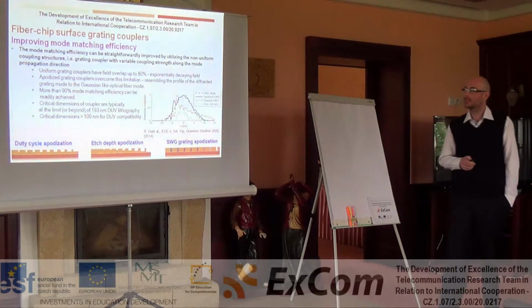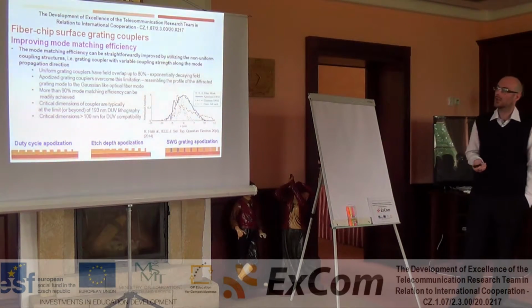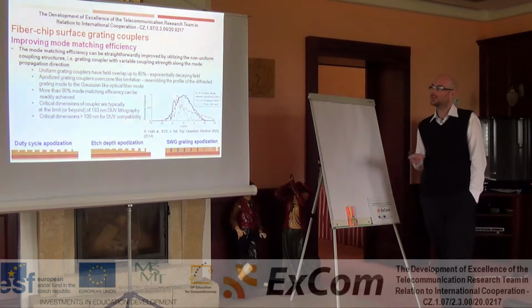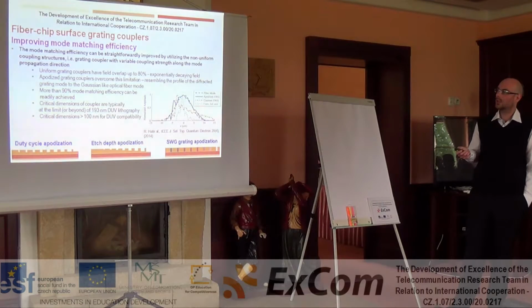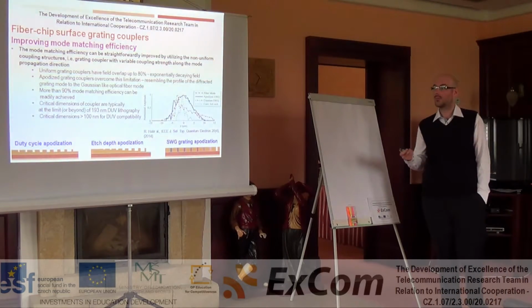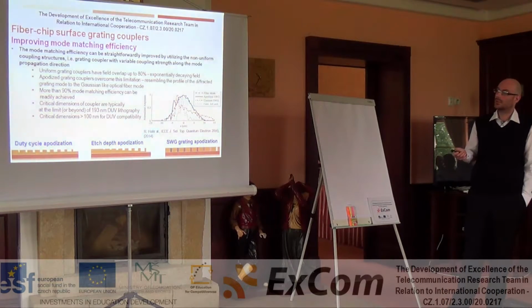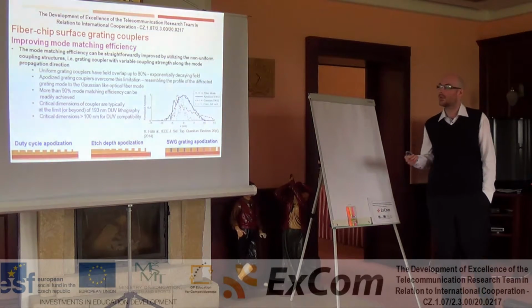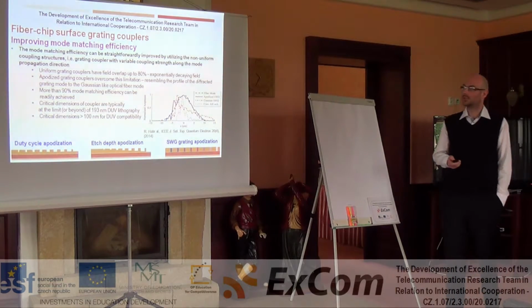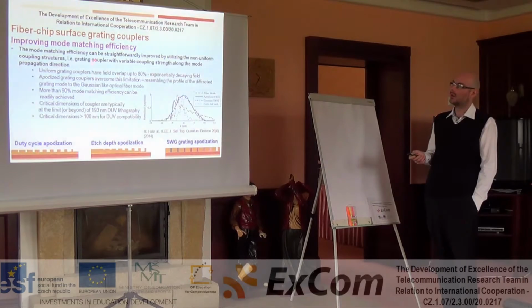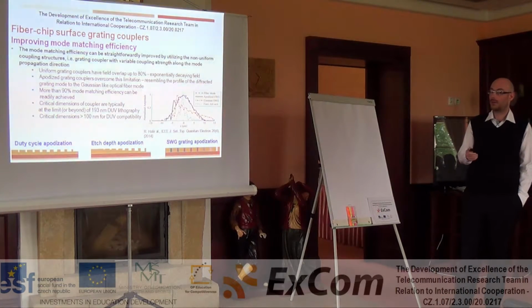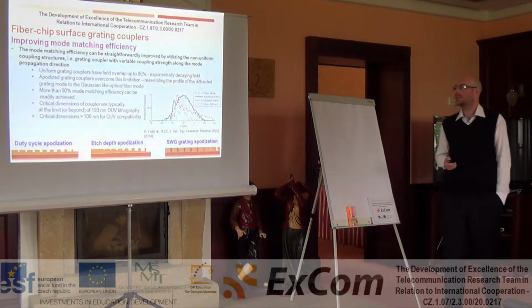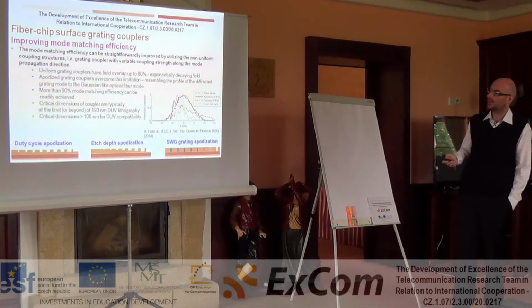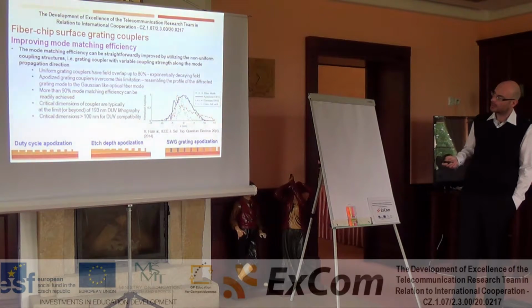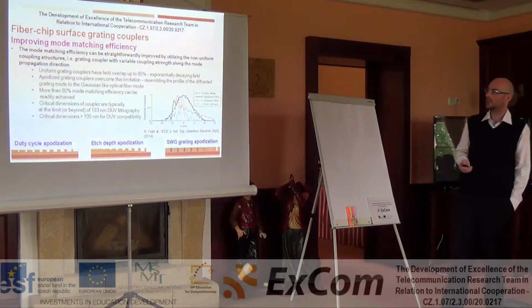Okay, the next source of losses is mode matching efficiency. The mode matching efficiency can be straightforwardly improved by utilizing the non-uniform coupling structure. That means it is a grating coupler that has variable coupling strength along the mode propagation direction. Uniform grating couplers have field overlap between optical fiber and the diffracted mode up to 80% and exponential decaying field, as you can see on this figure in this orange curve.